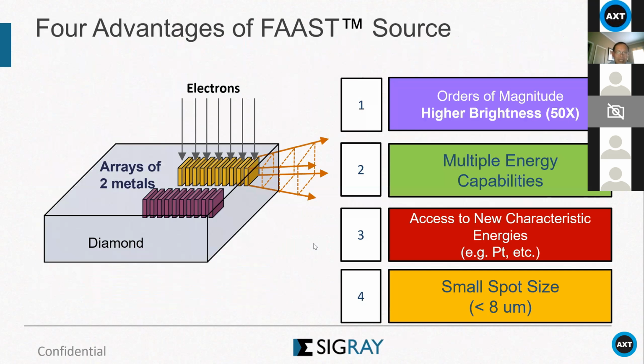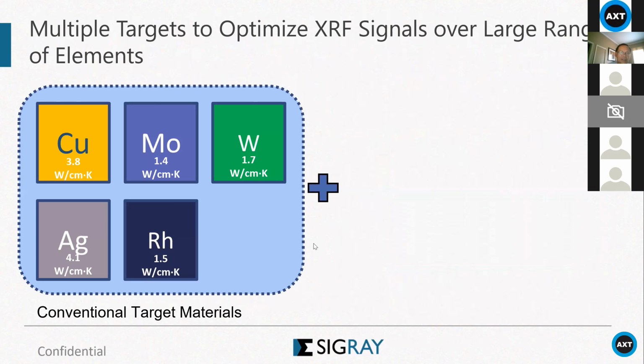So when we do that, this slide illustrates how we get multiple target materials on the same X-ray source. We microstructure the anode, and we have multiple different metals put inside the diamond. As a consequence, we produce orders of magnitude higher X-ray brightness, and we have multiple energies one can choose for excitation. You can easily switch from one target to another. And also we can get a very small spot due to our electron optics design. Multiple targets, for example, copper, moly, tungsten, silver, rhodium, and